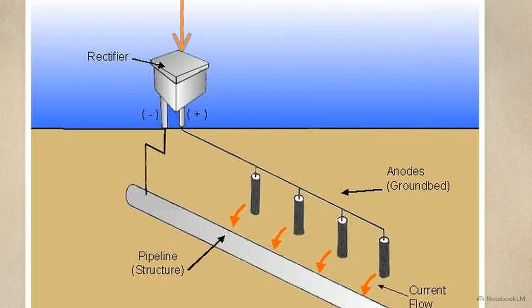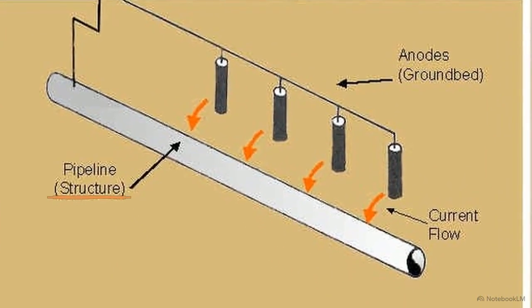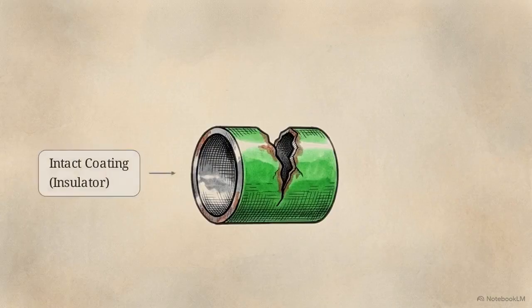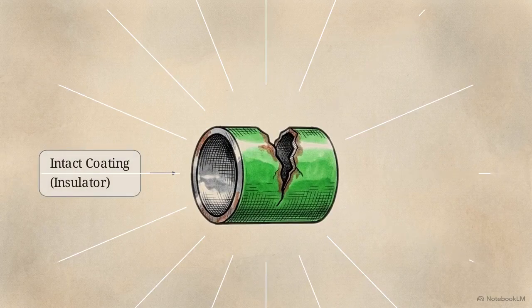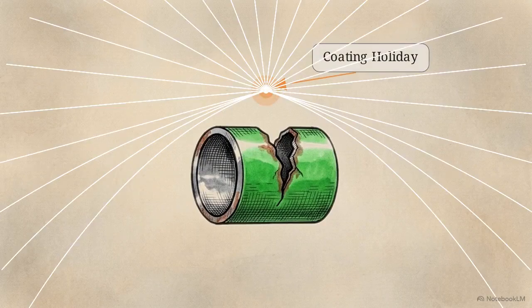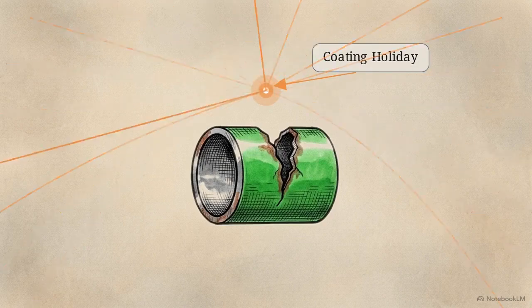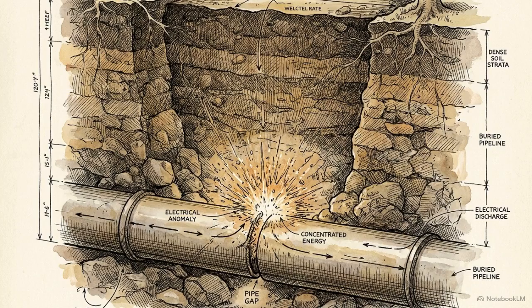A surface rectifier forces direct current through subterranean anodes into the surrounding soil. By bombarding the entire pipeline with electrons, the system artificially suppresses the release of electrons from the iron. Because the intact organic coating acts as an insulator, this impressed current concentrates almost exclusively at the microscopic coating holidays, where the bare steel is exposed. While a holiday is a structural vulnerability, its massive draw of ICCP current creates a distinct, localized electrical anomaly.